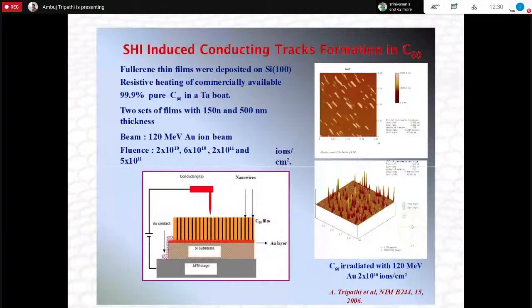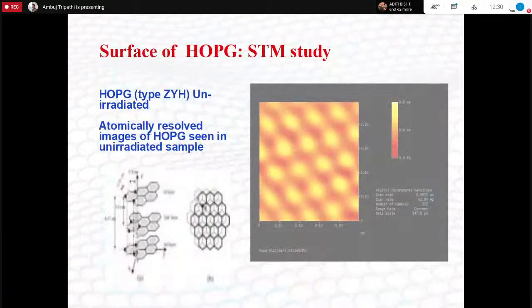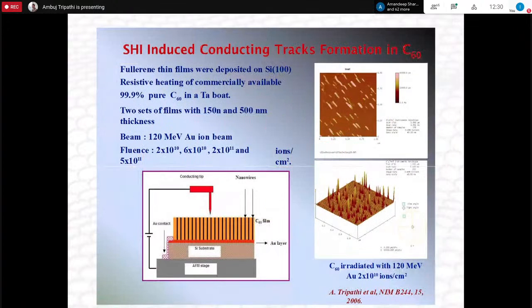At that time, what we were doing was looking at the conducting track. This was one of the earliest works we did using one of these attachments. This is with the commercial atomic force microscope which I showed you. One of the modes there is called conducting AFM. So this is a tip which you magnetize, and besides looking at the surface topography, you can also look at whether some of the portions are irradiated. This work was a continuation of some earlier work where we had seen that the surface becomes more conducting after irradiation. So we were trying to understand it, and trying to see whether we can see it in this conducting portion.